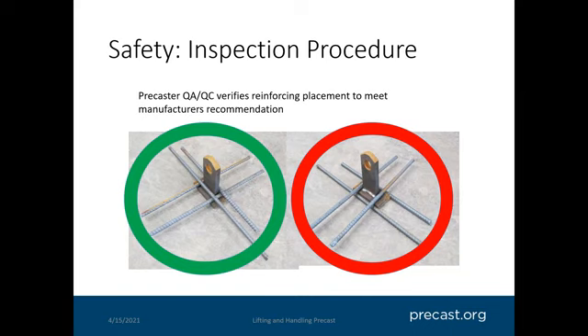One other thing to note is on these plate anchors, these are very commonly used for form stripping. That QA/QC checks to make sure that the reinforcement around these, the recommendation from manufacturers is that we use a number 4 bar, 18 inches long. And you can see in this, on the left here, you have your bars underneath on the actual plate. On the right, you can see they're on the ground, so that does no good for the shear cone. You're only getting the shear cone this way. You're actually getting a partial shear cone. This way, you actually get a full shear cone.